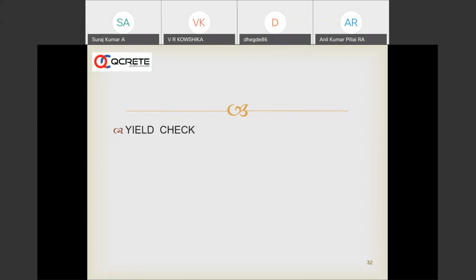And at least once every day, we need to take this yield check and match it with the weight of the concrete that we have batched in the truck. And we also have to check how much is batched as per the batch record. In the batch record, the theoretical recipe and the total batched material should match each other.